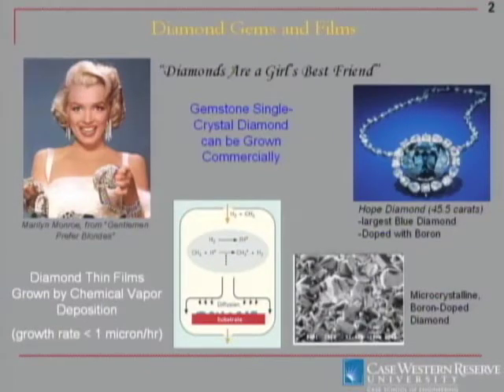This is, again, a thin film. You can grow a single crystal film like the larger single crystal diamonds, but you can usually only do that on diamond itself. What you tend to do is grow a polycrystalline film where you grow lots of little diamonds that coalesce to form a film, and there's not anything telling these little crystals to grow all in the same direction, so you end up with grain boundaries between them, as you see here.